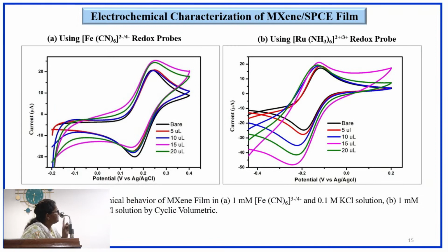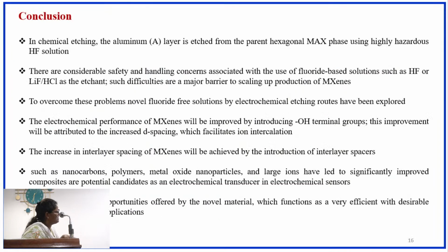Then the synthesized MXene was characterized electrochemically using both a positive and a negative redox probe. We chose both because our synthesized material is negatively charged, terminated with chlorine and hydroxyl groups. In cyclic voltammetry with the negative probe, the catalytic activity decreased because the negative charge of our material repels it. With the ruthenium redox probe, the catalytic activity increases because our material is negative, which enhances the catalytic activity toward the positive probe.